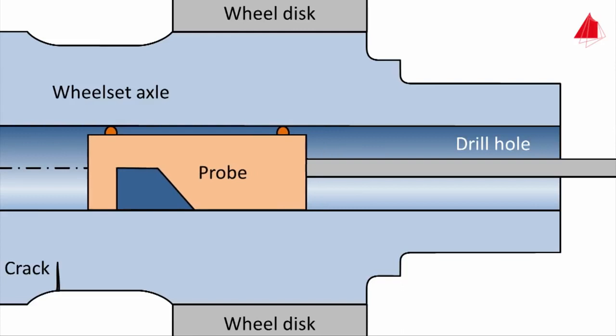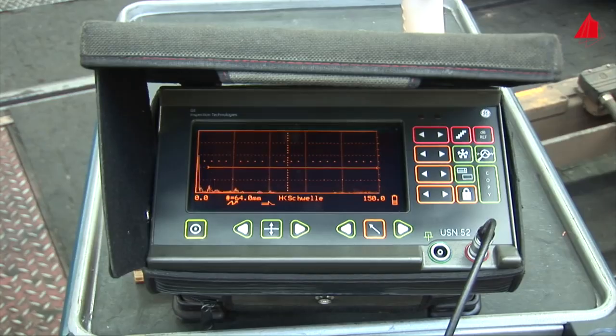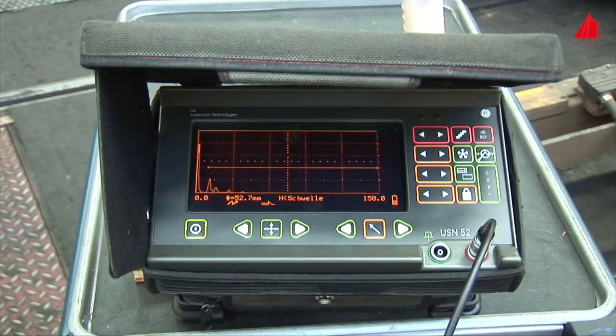It is important to note that also the shape of the wheel set axle may lead to an echo, for example at shoulders. These are so-called contour echoes. In this particular case, only contour echoes are recorded. No abnormality has been detected.